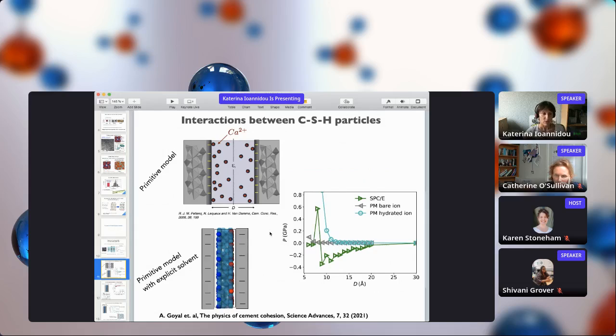In a recent model we came up with, again with the idea of coarse graining, we have a system that doesn't carry all the atomistic simulation information. We don't have all the different species, calcium, silicate, that are forming the planes. We only have two planes for the CSH with the right surface charge, and inside we have the calcium ions that are making our simulation electroneutral. The different colors just denote the side on which the ions are.